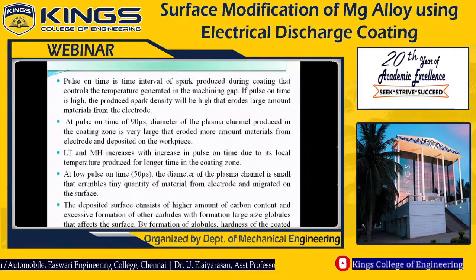If pulse on time is high, the produced spark density will be high, which erodes a large amount of material from the electrode. At a high pulse on time, for example 90 microseconds, the diameter of the plasma channel is high, so that removes a high quantity of material from the electrode. LT and MH increase with increase in pulse on time due to the local temperature produced for a longer time in the coating zone.